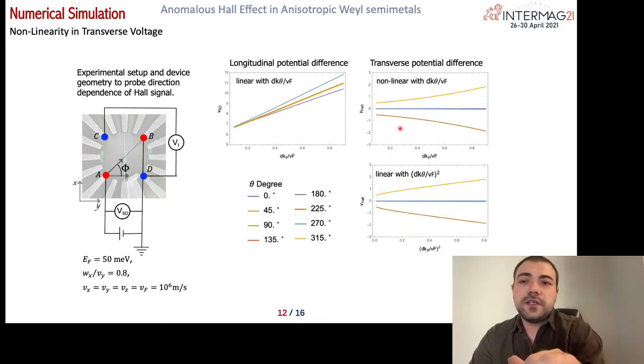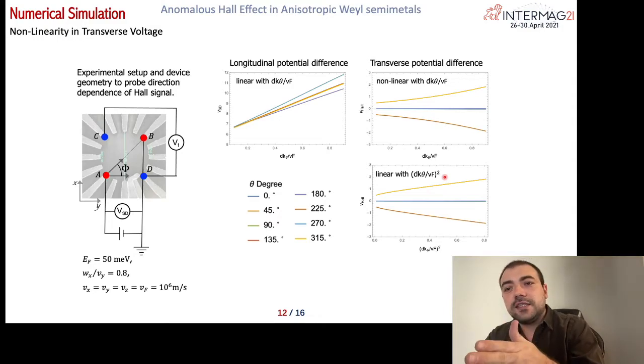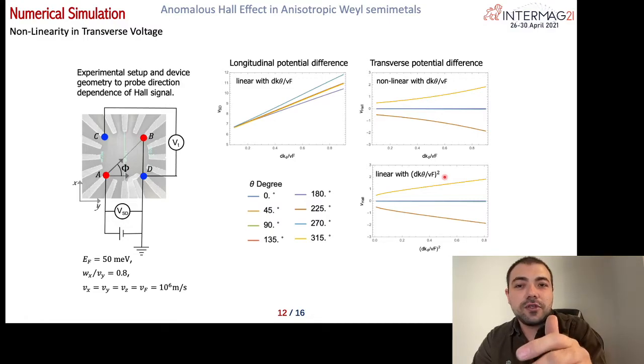As a result, the extracted voltage values shows that there is non-linear relation between longitudinal and transverse voltages. And the transverse voltage is almost linearly dependent on the square of longitudinal voltage. We may explain this behavior such that the electrical field is breaking the transport symmetry and the transverse conduction symmetry is already broken. So normally only broken transverse symmetry would cause linearly dependent Hall signal. But here we got another effect in play and that broke the transport symmetry. So the coupling of these two broken symmetries may be the underlying reason of the non-linearity in the Hall voltage.